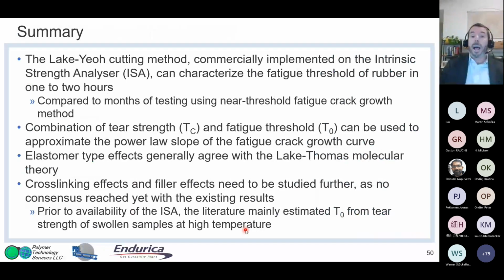I showed you the Lake-Yeoh cutting method that's now commercially implemented on the intrinsic strength analyzer. It can characterize a fatigue threshold in about 1 to 2 hours. And if you compare that to near threshold fatigue crack growth, which takes months, now we have a really quick method to assess this key parameter of rubber. If you take that parameter and you combine it with a tear strength, you can get kind of a first pass approximation of the power law slope for fatigue cracking.